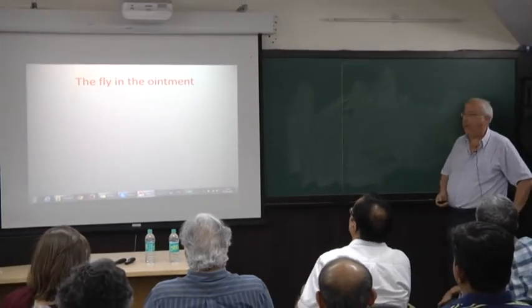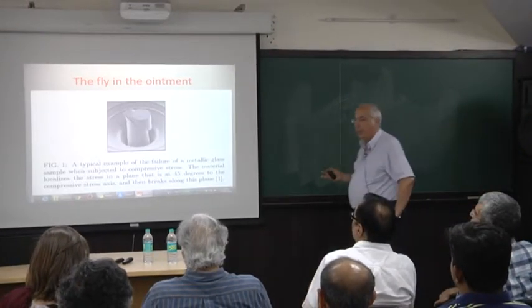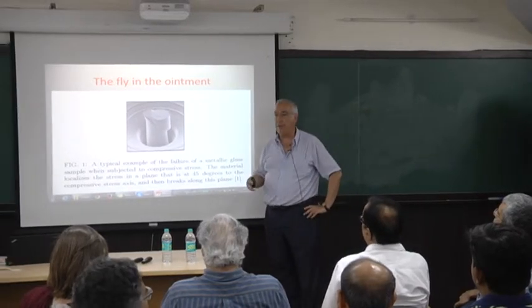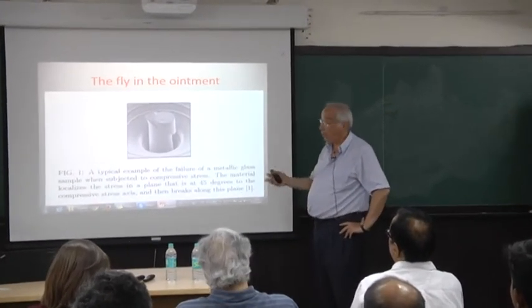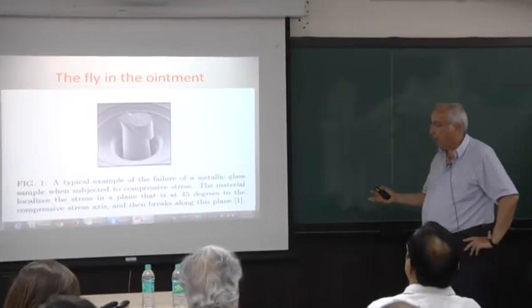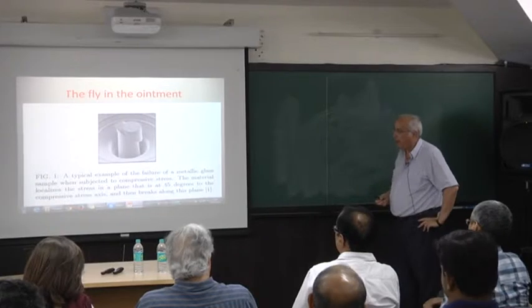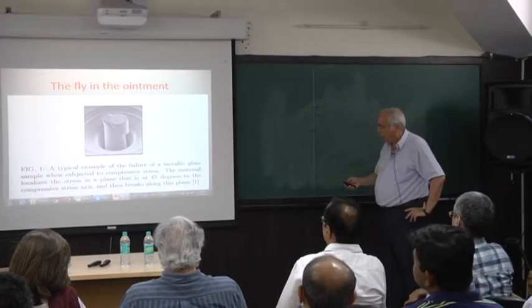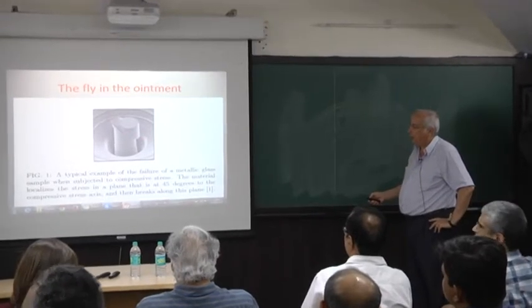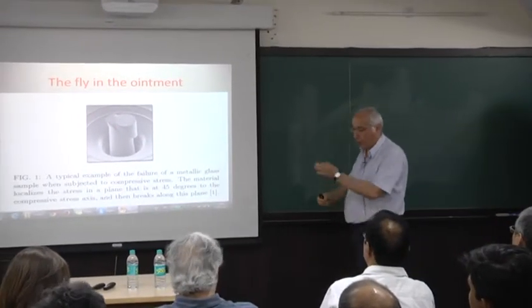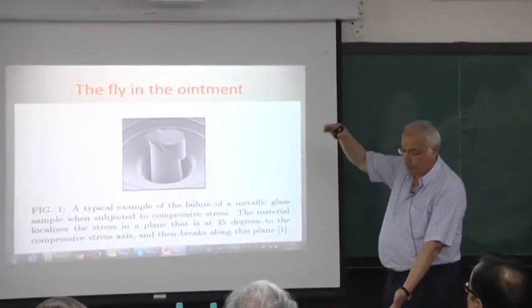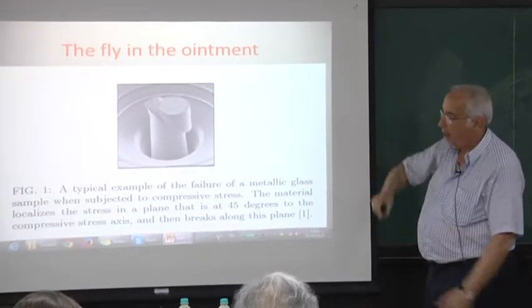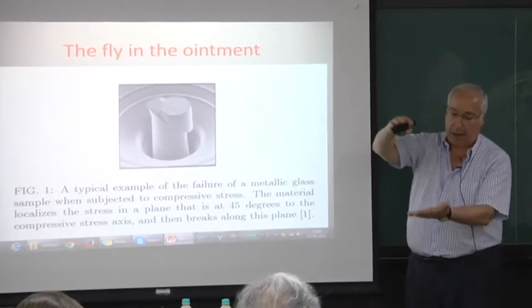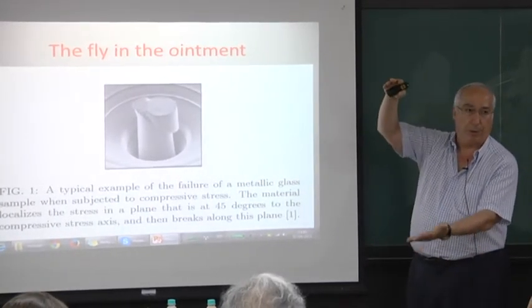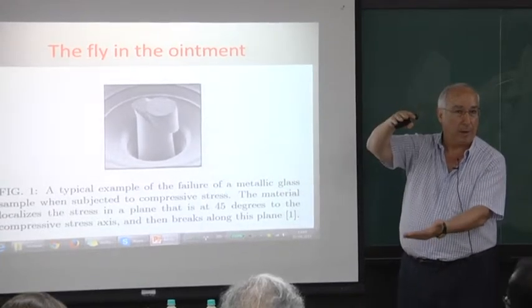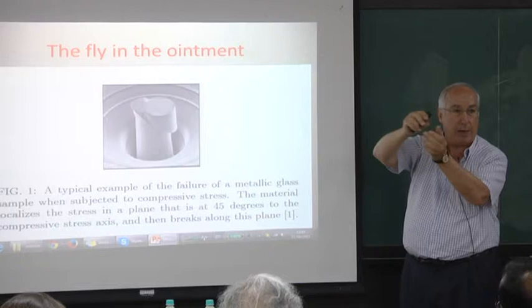The fly in the ointment is this. These materials, which are so springy and have such a soft response to magnetism and such good response mechanically, have a tendency to break. And they break in what we call a shear band. So this is the phenomenon of a shear band. This is a small rod of metallic glass, which is pressed this way. So you compress it. And even though you have a strain which is distributed uniformly over the whole sample, it has a tendency to concentrate all the strain on a thin layer.